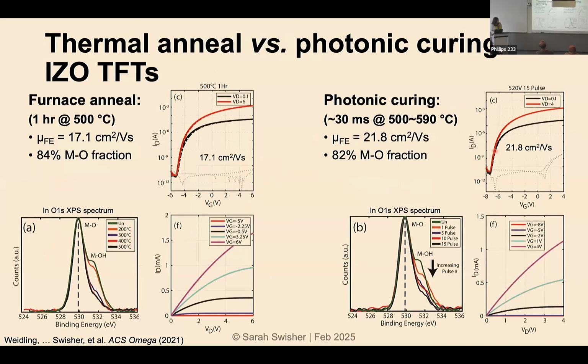we showed that photonic curing can be used to process transparent oxide materials just as well as an hour in a 500-degree tube furnace, if not even a little bit better. You can see here that our field effect mobility is just slightly higher in our photonically cured samples. And when we look at that conversion, that oxide to hydroxide ratio, it's almost exactly the same in our photonically cured sample as it is in our furnace annealed control sample.